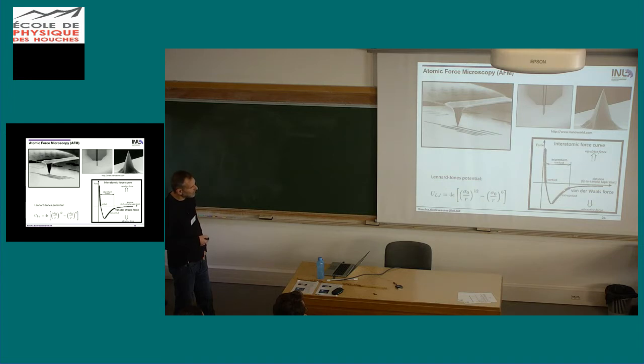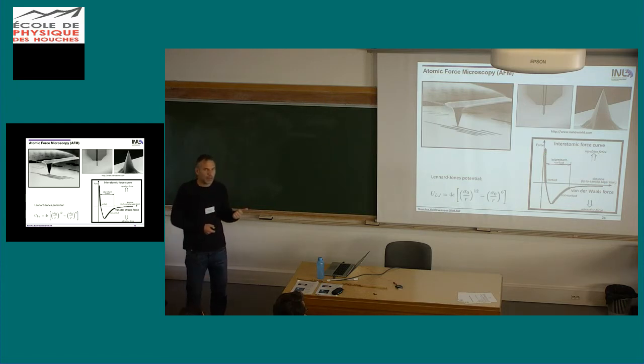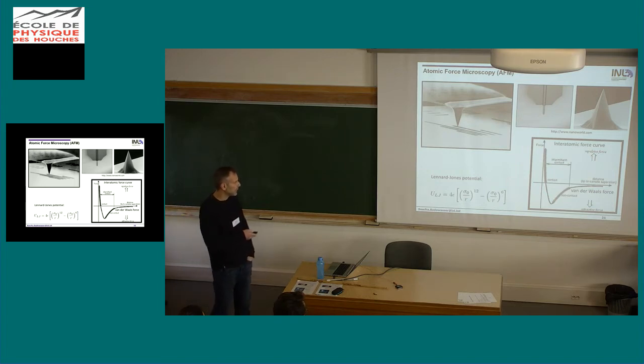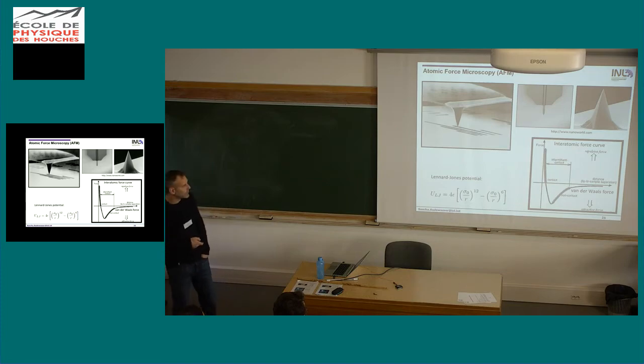And at some point, if you go too close, you get a lot of attractive forces, but then it converts into repulsive forces. So that's when you go very close and you get essentially a Pauli repulsion between the electron clouds of the tip and the sample atoms. And this part of the curve you can model or approximate by the Lennard-Jones potential, which is a phenomenological way to describe these forces.